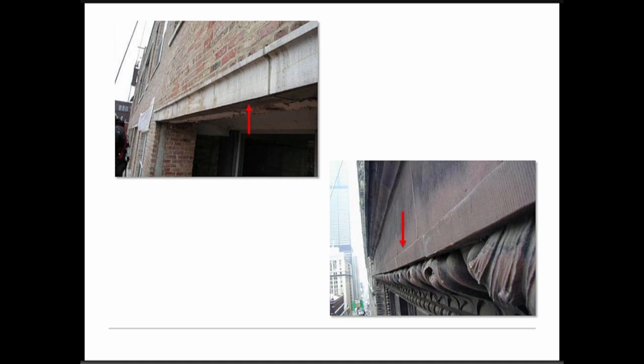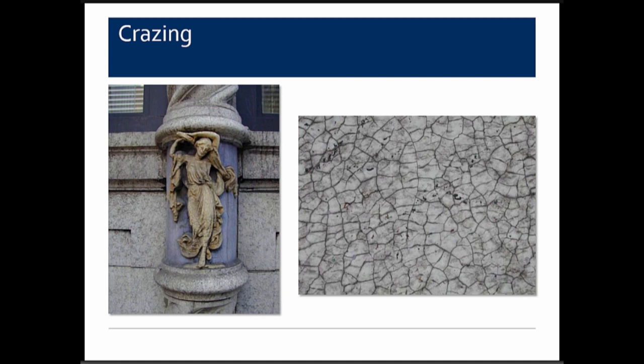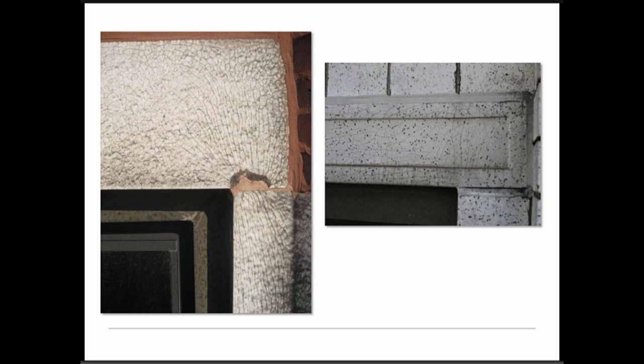Lintels, being hung, are often prone to visible displacement, especially in the center. Units installed with horizontal rods may have been tweaked and torqued during installation with J-hooks, with mortar between units also helping hold them into place, resulting in sagging or slight in-and-out movement of the lintels. Crazing is another distress type visible in the glazing of units, caused by stress or production issues.